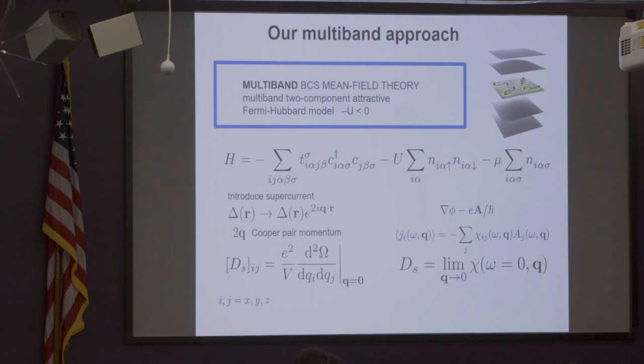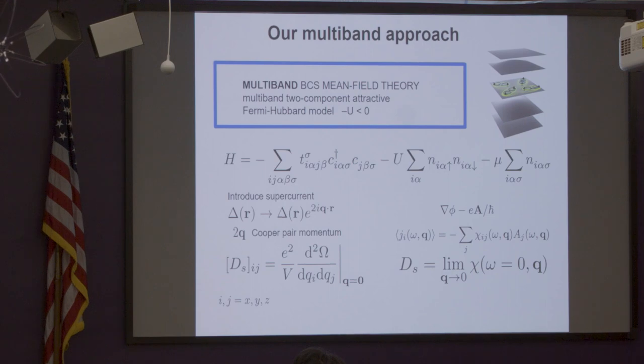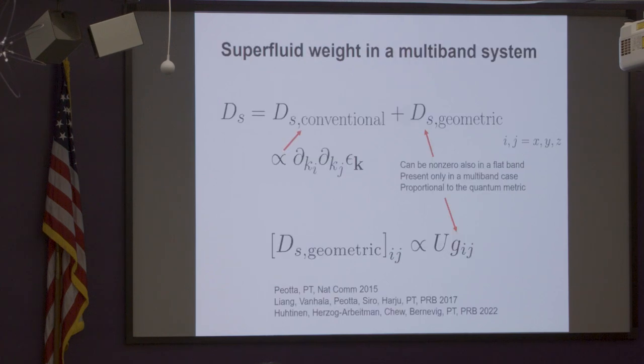There is also an alternative way of getting superfluid weight: you can think about it as a linear response coefficient to the vector potential. You apply a vector potential, you get some current, and this kernel gives you the superfluid weight at some limit. This gives the same result, providing a nice sanity check — always calculate it both ways. We did this to this Hamiltonian and here is the main result.